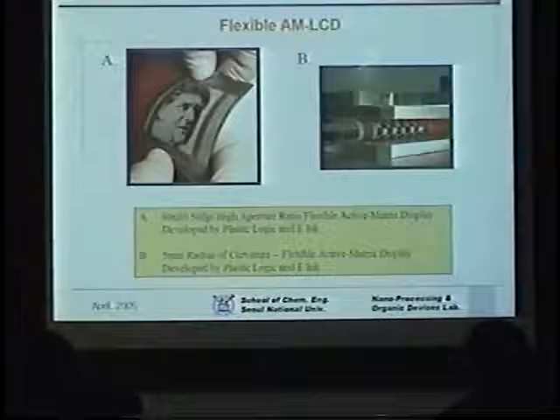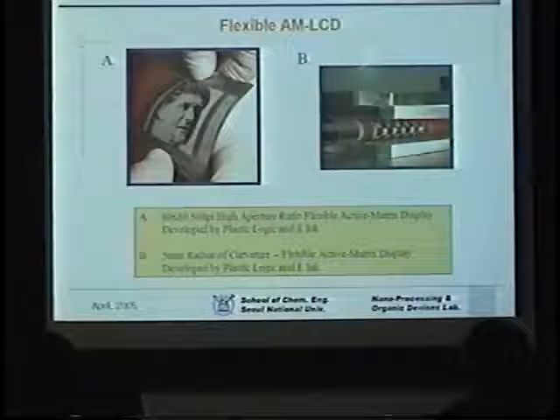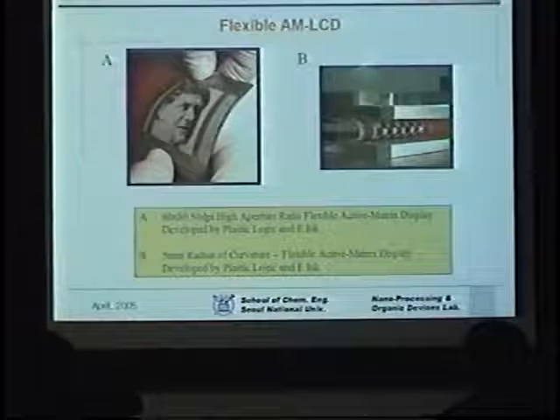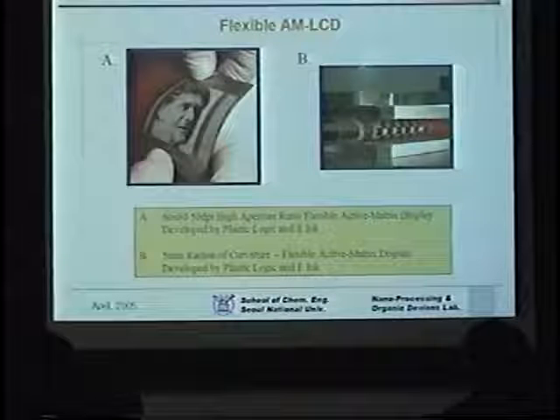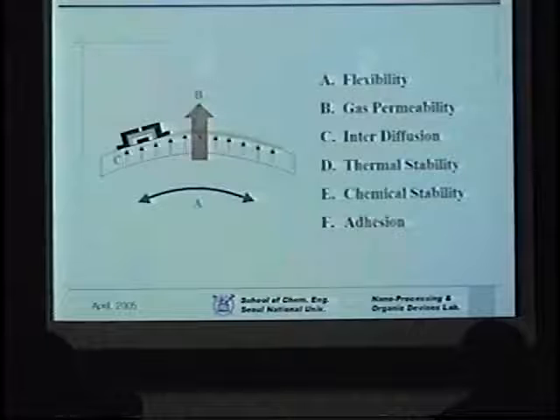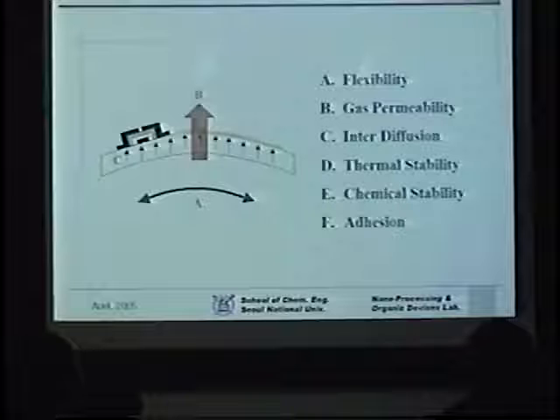When we talk about flexible display, of course we need flexible substrate. Shown here is the active matrix display made by Plastic Logic and E Ink. And of course, since it's flexible, you can bend it around. The issues related to flexible substrates are really the requirements that the substrate has to meet, and these are listed here. But the most important thing, foremost, is the ability of the substrate to resist any permeation or diffusion of water and oxygen.